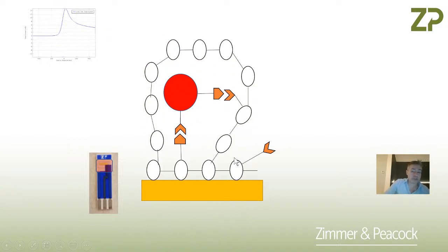And then because you have a mixture of monomers going in here, you can end up arranging the monomers due to the functional groups on the template. So now you have a site that I would say is more specific, because this molecule can only go into this pore when it's binding here and it's binding here, and that really helps with the specificity of it. So if you wash it away, then you're left with something that's, again, more like an enzyme catalytic site, where you have the right shape.